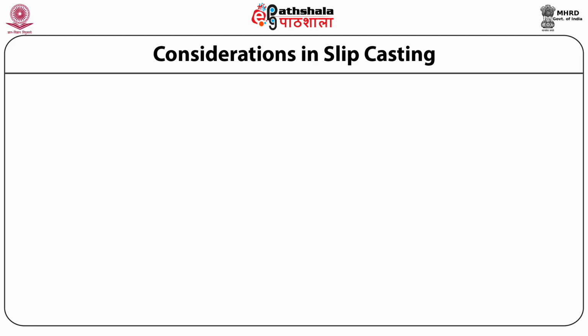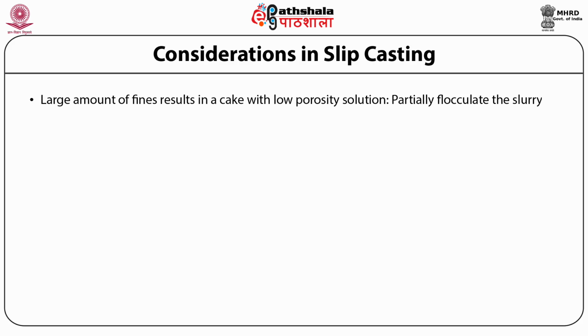Now there are some considerations which we should keep in mind in slip casting. Some factors which are considered while formulating a slurry for slip casting are: first, a large amount of fine particles in the slurry will produce a cake that has a low porosity, and so the casting rate will be slow and non-uniform. To avoid this, the slurry can be partially flocculated.